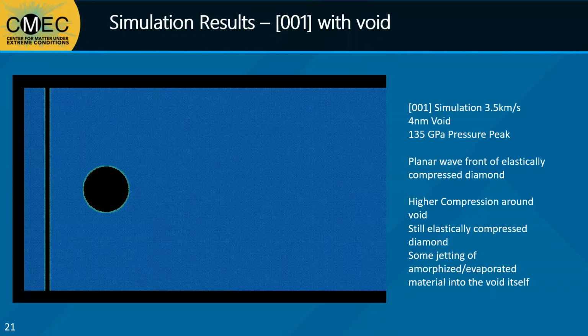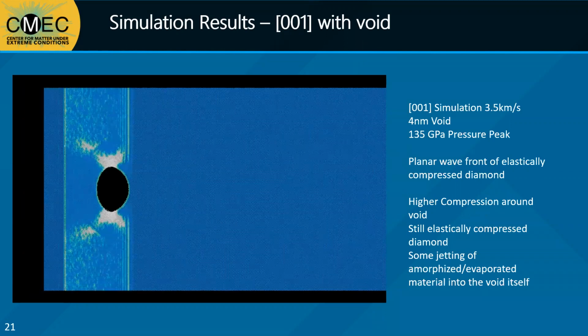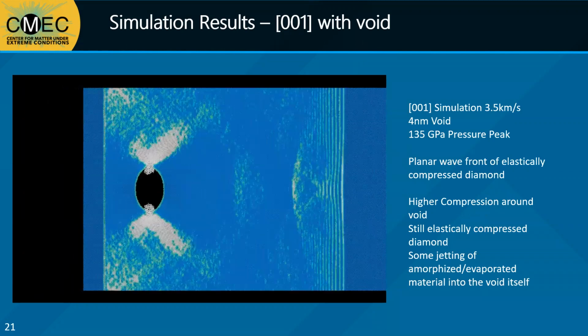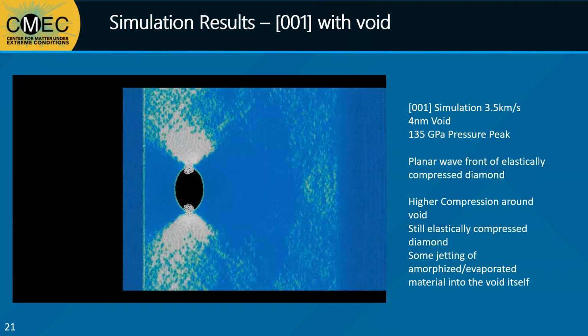When a void is introduced, which acts as a stress concentrator, it appears that there is some activity above and below the void. However, this is simply the identification algorithm for the diamond cubic phase no longer working on the highly compressed areas. It is simply so elastically compressed that it could not be recognized. There are still no dislocations forming in this simulation, although there is some jetting and amorphization of material into the void.